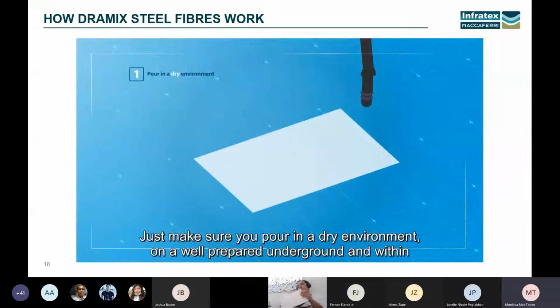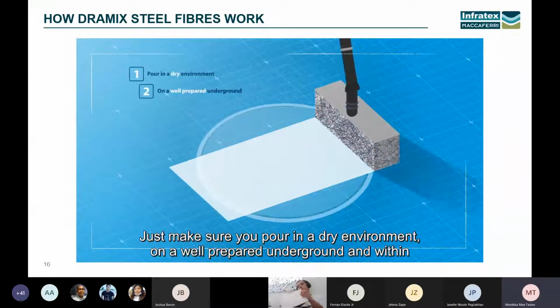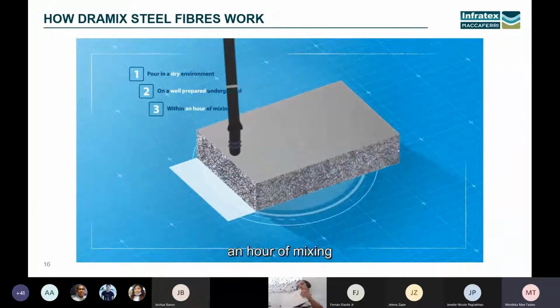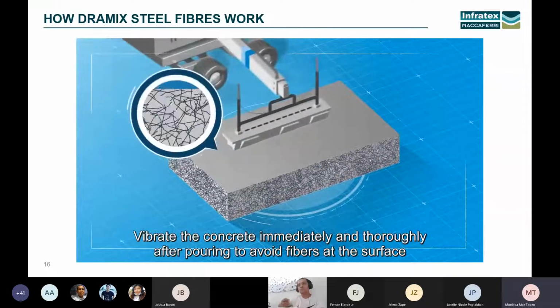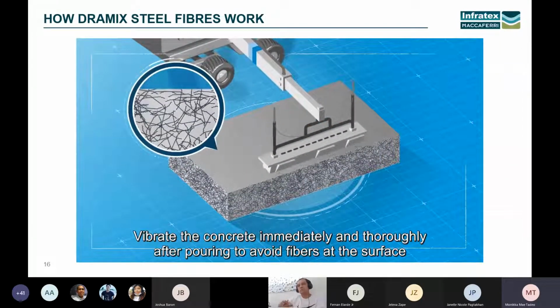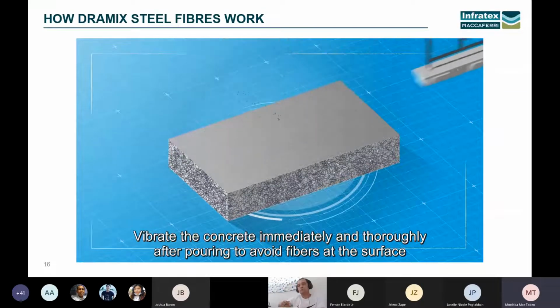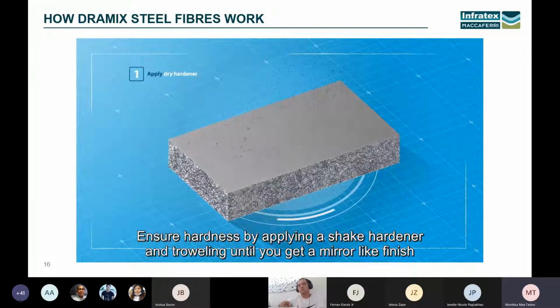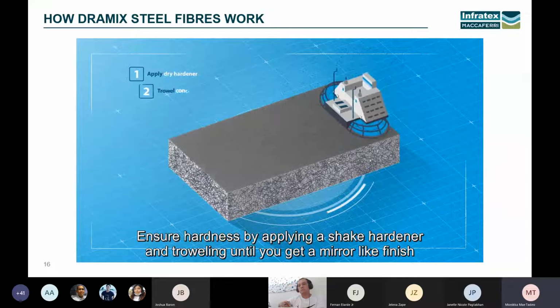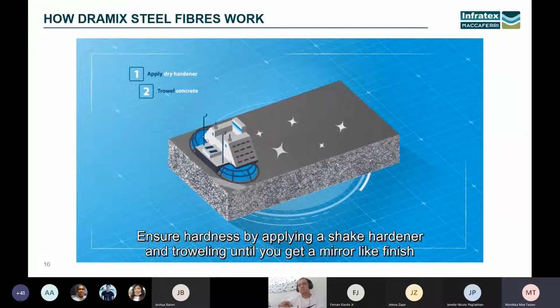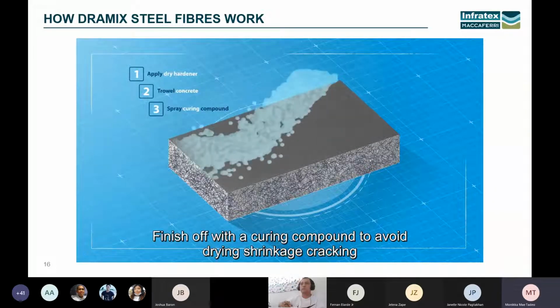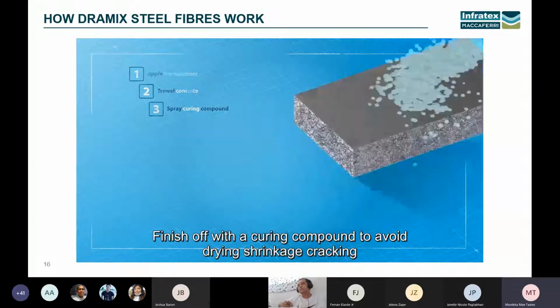Just make sure you pour in a dry environment, on a well-prepared underground, and within an hour of mixing. Vibrate the concrete immediately and thoroughly after pouring to avoid fibers at the surface. Ensure hardness by applying a dry shake hardener and troweling until you get a mirror-like finish. Finish off with a curing compound to avoid drying, shrinkage, cracking.